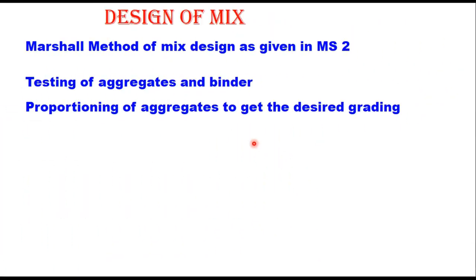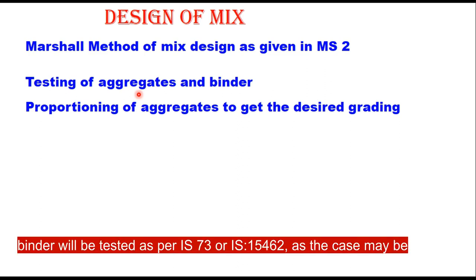For mix design, the Marshall method as given in MS-2 series is recommended for designing the job mix formula for bituminous concrete. The first step is testing of aggregates and binder: physical tests on aggregate including flakiness index, elongation index, cleanliness, water absorption, strength parameters and durability. Binder is tested as per IS 73 for viscosity grade binder or IS 15462 for modified binder.